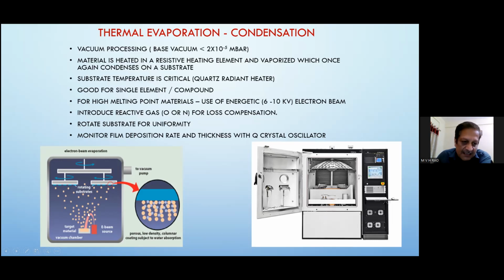So using that magnetic field, the charged electrons that are thermionically generated by heating a tungsten filament are also accelerated by using high voltage. Those high voltage accelerated electrons bend through the magnetic field in the form of an arc, and get focused onto the material that we want to deposit in the crucible. In that crucible, the high melting point material is put, and when this high energy beam is focused on it, energy is imparted and it will melt and then vaporize further. And then the vapor atoms come up to the top.